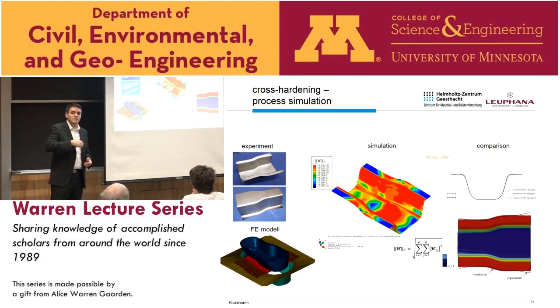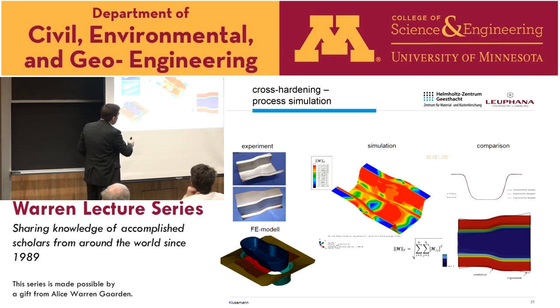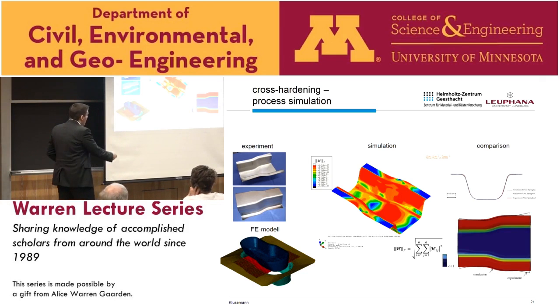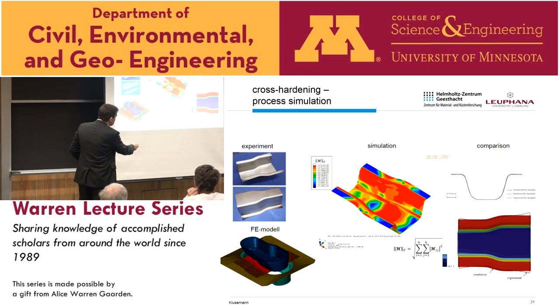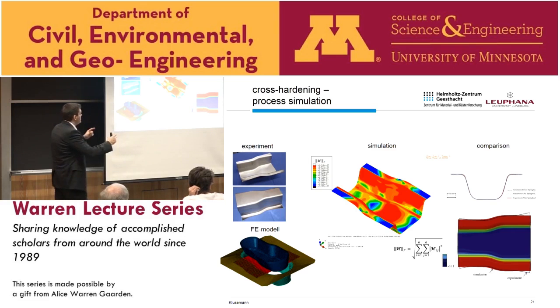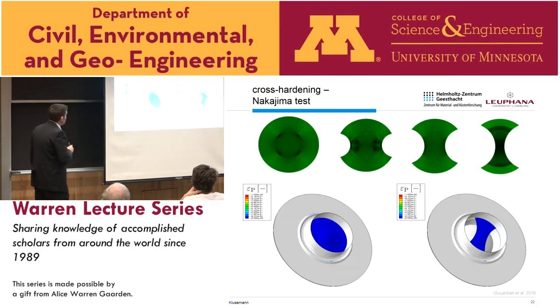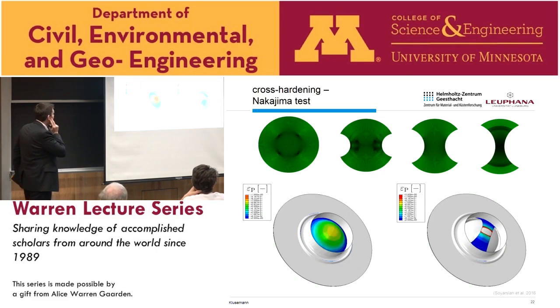We then did, of course, some comparison regarding the shape. As you can see here on the right, we in particular looked at the effect of the spring back in this kind of samples. And at least in the principal shape, we could do that quite correctly. However, of course, there was some slight deviation at the outside surface. But at least from the cross-section, we got a very good agreement between simulation and experiment.